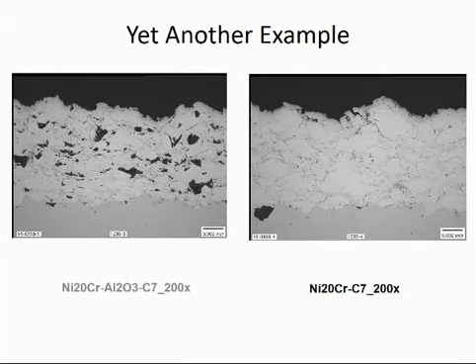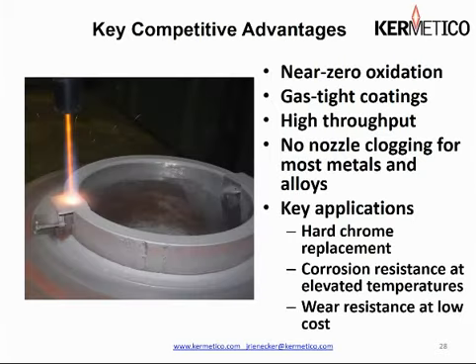Here's another example, same thing. This is a nickel-chromium alloy with aluminum oxide, and they're both at 200 magnification. The one on the right has no aluminum oxide, and even though the one on the left looks worse in testing, it turns out to be a much better coating. Gas permeability testing, hardness, ductility, K1C, all of that stuff is much better with the aluminum oxide in it.